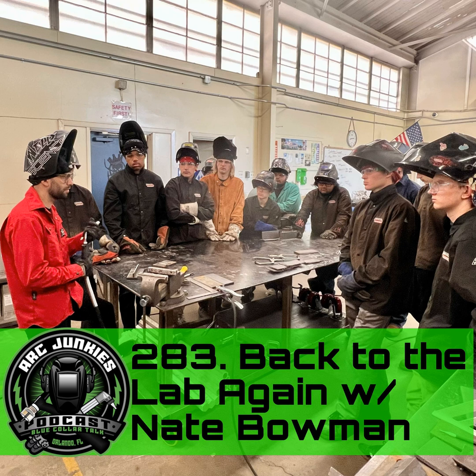There was slag in the root. Scott Prince and I ran it all the way up to like 700 inches a minute in the flat, trying to put a 5/16 fillet weld in with 75/25, not CO2, and we still got slag in the root.